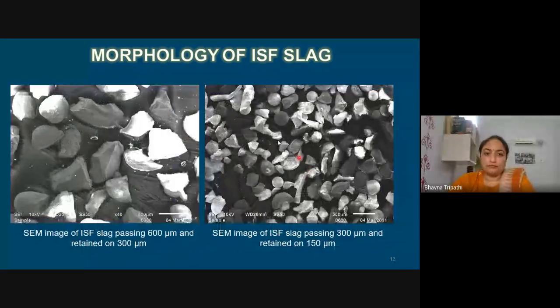Another similar picture. I have studied this for slag particles which are less than 600 micron size. This one shows the particles which are retained on 300 micron, and on the right hand side these are the particles which are retained on 150 micron. What we can see clearly is as the size reduces, the irregularity in the surface reduces, and these surfaces more closely resemble sand. However, the surface is rough. Natural sand is weathered rock, and therefore the surface is very smooth.